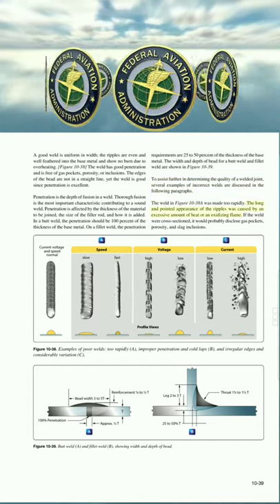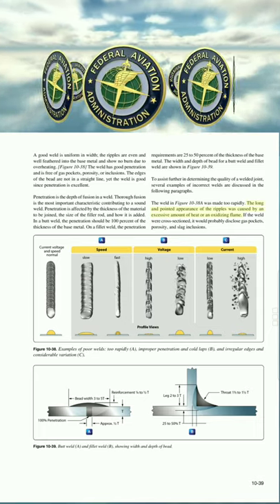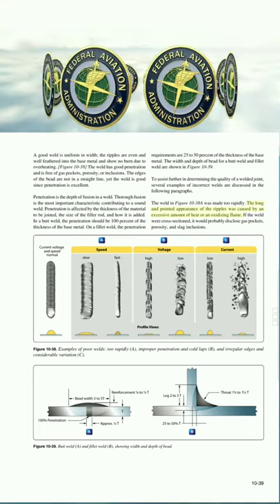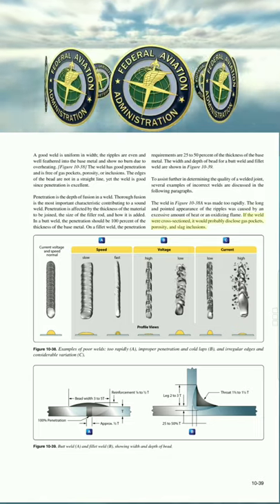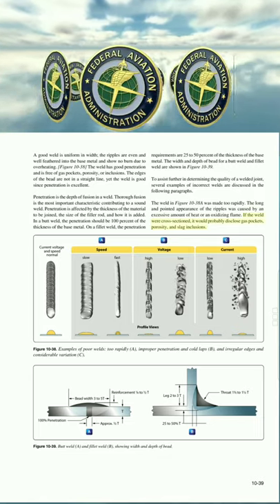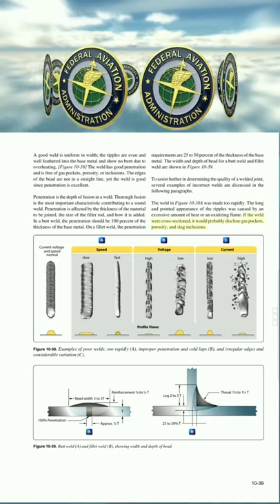The long and pointed appearance of the ripples was caused by an excessive amount of heat, or an oxidizing flame. If the weld were cross-sectioned, it would probably disclose gas pockets, porosity, and slag inclusions.